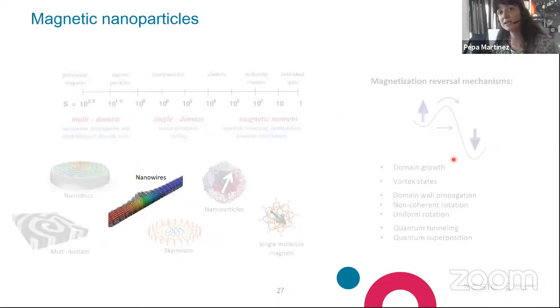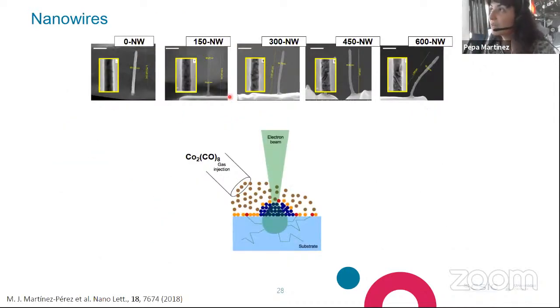Let's now reduce slightly the size of our objects and the dimensionality. Let's go to one dimension, studying nanowires. Okay, here you can see a set of 5 nanowires that were grown by means of focused electron beam induced deposition of cobalt, leading to these nice three-dimensional structures going out of the plane. This technique is very nice, but it usually yields structures having very low metallic content. So our colleagues wanted to study if they could enhance the content of cobalt by an annealing procedure in which they anneal these nanowires at higher and higher temperatures, up to 600 degrees, to see whether this increases the crystallinity and the amount of cobalt.